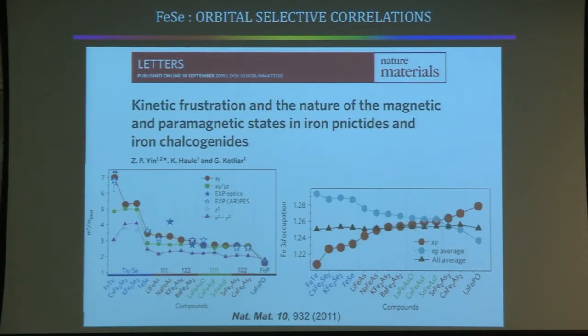Okay, so where to look? This is one of Gaby Kotliar's maps of the correlation strength in the iron compounds. And over here, for example, in the iron arsenides, iron selenides, you actually start to get very strong electron correlations. So a place to look for orbital selectivity would be over here, orbital selective superconductivity and orbital selective Mott phases. I showed this to Gaby a couple of weeks ago, and those of you who know him know what he would say. He said, well, I already know that orbital selective Mott phases exist, so I don't need experiments.